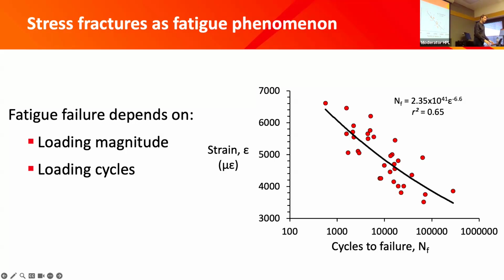What's important to see here is that this is a highly nonlinear relationship. The x-axis here is on a logarithmic scale, which basically means that small changes in the y-axis lead to big changes in the x-axis. I'll just show a quick example of that. If we load our bone at about 6,000 microstrain, it's going to last about 1,000 cycles. If you reduce that strain to about 4,800, so not even half that magnitude of the initial load, it lasts 10,000 cycles. So not even a 50% reduction in the loading magnitude leads to a 10-fold increase in the number of cycles that that bone can last until it fails.